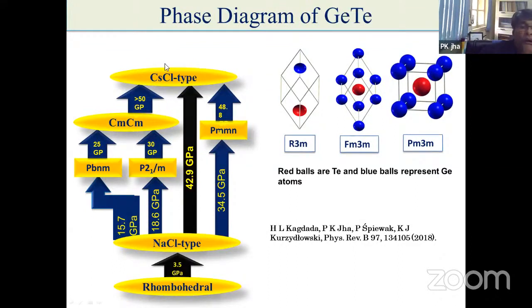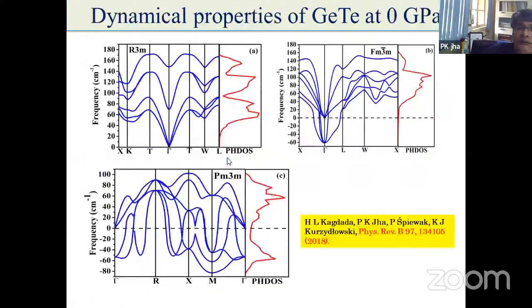To go from rhombohedral to a CsCl structure, there are 4 parts, and this is the simplest part. So let us talk about this, right? You have rhombohedral R3m, you have NaCl Fm3m, and you have the CsCl structure Pm3m. And therefore you can see that rhombohedral to NaCl it goes at 3.5, and from NaCl to Pm3m, in fact, this is some mistake. So it is 34.5 GPa, right? So there is a phase transition in GeTe.